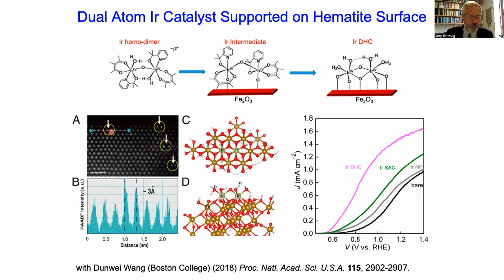see these bright spots, two bright spots adjacent to each other. Here's the intensity profile going along this trajectory, this line here. And we see only dimers. So there's a dimer here, another dimer here. And these dimers are extremely stable. So we can image the surface both before and after photocatalysis, and the dimers haven't moved. So they're extremely tightly anchored to the surface.